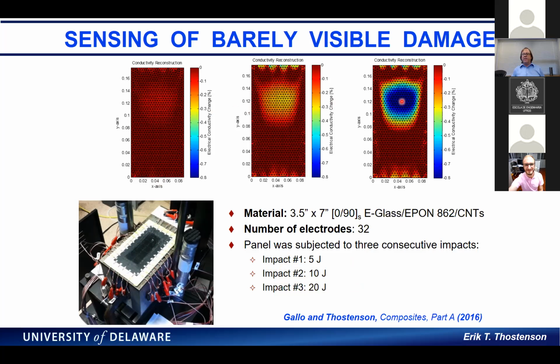that damage has formed. And at this point, at the highest impact, you could see a little dent in the composite, but at the lower energy impacts, the composite looks fine. But here we're certainly picking up that matrix cracking that is occurring during the impact.